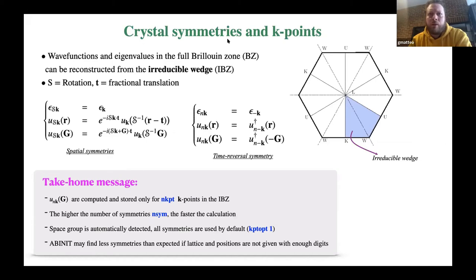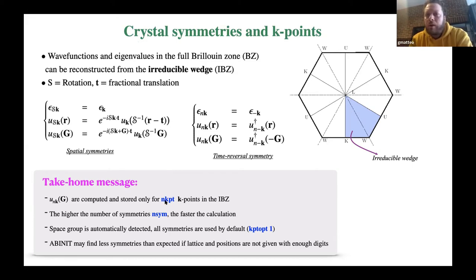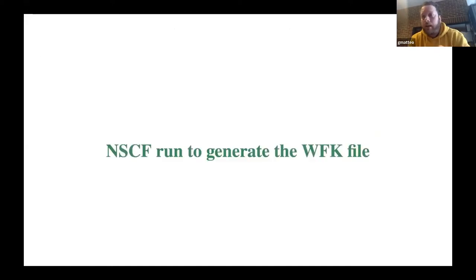Regarding symmetries: we take advantage of the fact that the system is invariant under certain rotations and fractional translations to reduce the computation to a subset of the full Brillouin zone, because eigenvalues and wave functions can be reconstructed at runtime from the irreducible wedge. In Abinit we call this number of k-points NKPT. These symmetries are very important because they reduce memory requirements and accelerate the calculation.